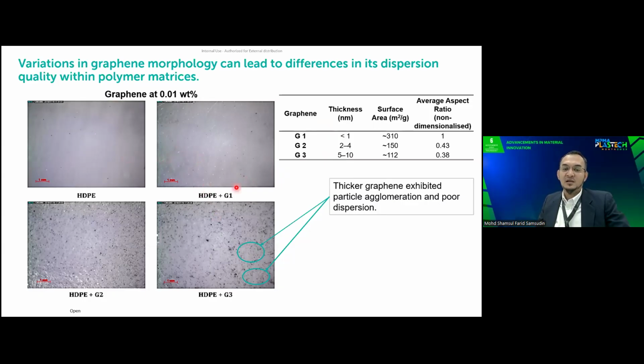So for G1, the finest grade of graphene, we almost can't see any graphene dispersion here, because we believe that because of the finer size of the graphene, it blends well and disperses well. So we only can see very small dots of black color here, the black graphene. And for G2 and G3, we notice that the dispersion of the graphene is good, but we can see big particles scattered around this film, and some of them are quite big in size. So we believe that having this coarser graphene layer or thickness also will affect the dispersion of graphene in the polymer film or HDPE.